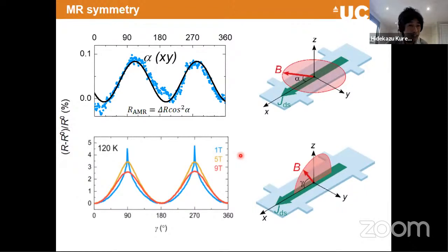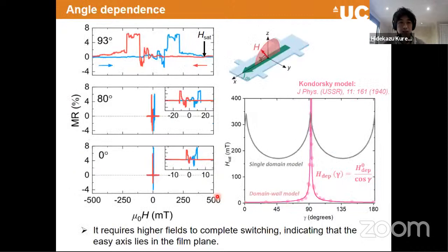And I just want to mention also that this kind of behavior can also be observed in the graphene system. Right, so let's go back to magnetism. We can see that this switching mechanism is very, very complex, because this jumpy behavior tells us about some change of the domain wall and so on, but it's very difficult to use a macro spin picture to explain how it happens.